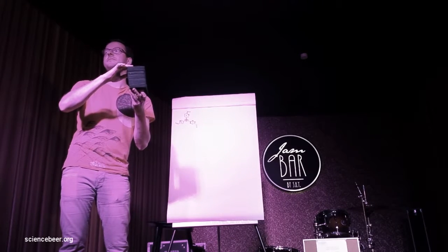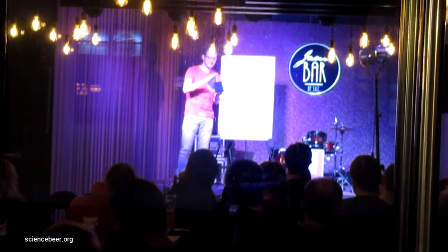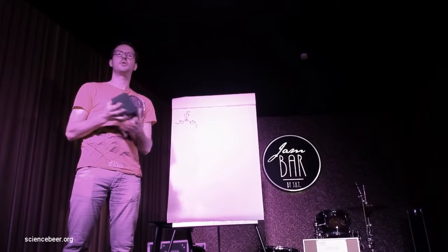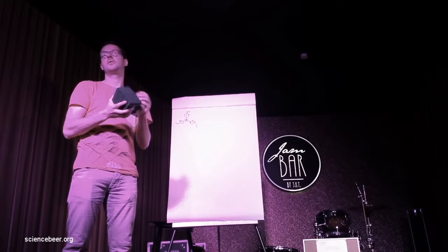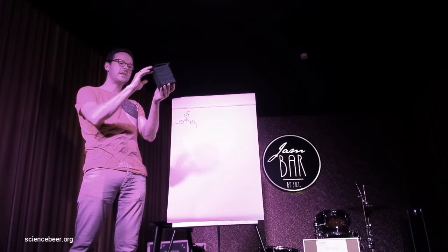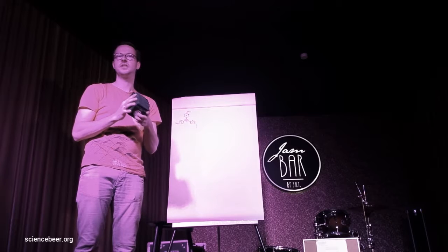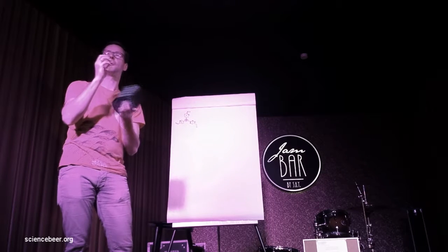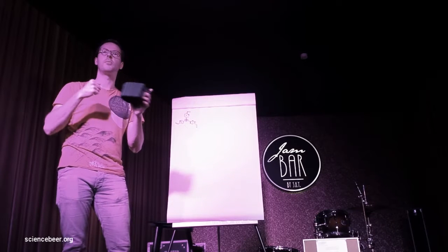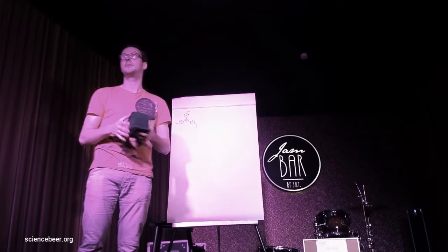Considering this is graphite, this is in a pencil. There are several methods to get this layer, but in general they stick together. All are with force. For example, in a dispersion, so you put this powder just in a solvent, it will not dissolve. We put it in an ultrasonication bath, for example. So then the solvent can intercalate here inside, and in the end it rips off. Or for example, in a ball milling machine, you put this powder in a small reactor with some balls, and then it shakes all the time.